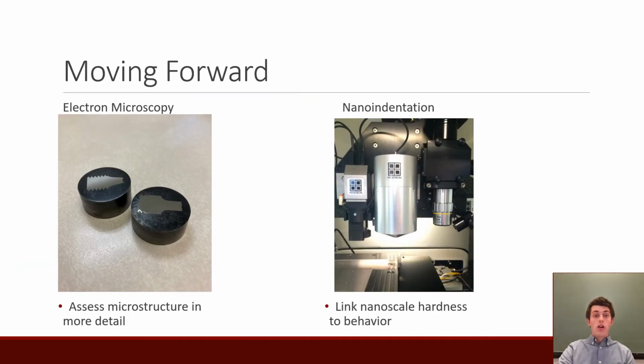So having done that test, where can we look forward? The first step would be to move to electron microscopy so that we could assess the microstructure in more detail. This would allow us to look more closely at the behavior of those identified niobium carbide particles on a smaller scale. In addition, it would allow us to see other features of note, such as the delta phase or the grain boundary fractures that were discussed earlier. Linking the locations of these, as well as identifying them, could provide more insight and include how the relative distance of these might have compounding effects on the material failure.